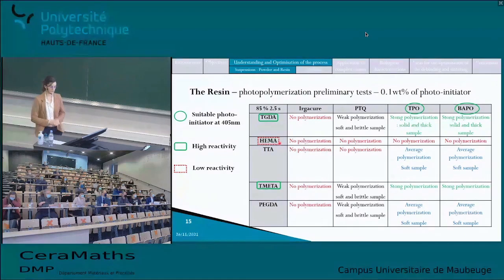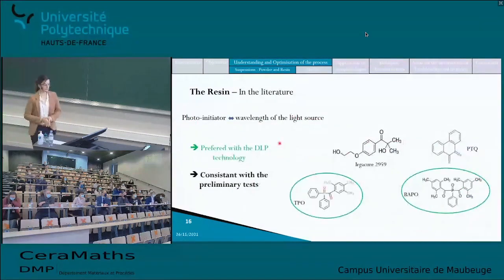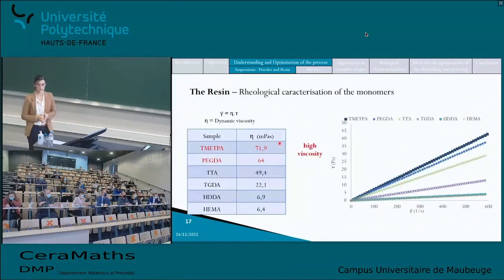So this was consistent with the preliminary tests. I added to that some rheological characterization of the monomers because the viscosity can also impact the reactivity of the monomers and the viscosity of the suspension. And as the goal is to have a good reactivity and a low viscosity of the suspension, I realized that the TMET-PA and the PEGDA had too high viscosity. So I decided not to pursue the experiment with these two monomers, and I finally selected only 4 different monomers